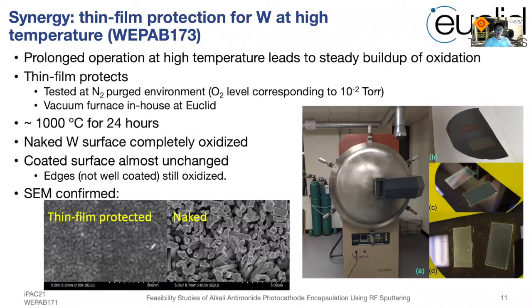Without measuring in a very systematic way the protection effectiveness of boron nitride for copper or any photocathode, we want to bring up the synergy of our recent thin film studies. In this study, we investigated the thin film protection for tungsten at high temperature. And this work is presented in another poster of mine.